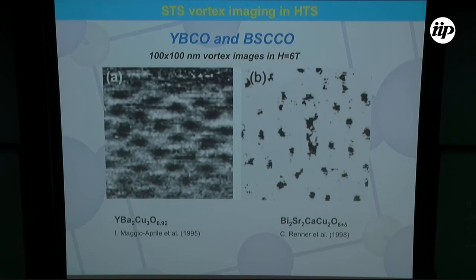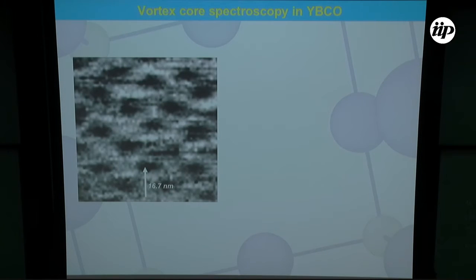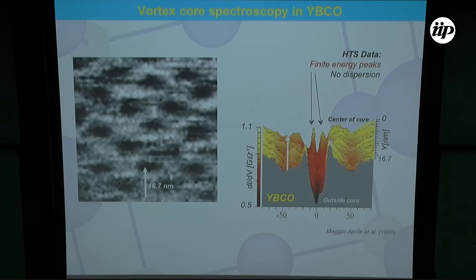Vortices have been seen in a number of cases. This is YBCO and BSCCO. You see the vortices are quite tiny, and you can compare the size of the cores with the ones of niobium diselenide, and due to the fact that the coherence length is really small in the cuprates, the cores appear really small in the images. We usually have non-ordered vortices, so disordered lattices. And for the spectroscopy, this is for YBCO, a trace taken from the outside to the inside of the core will show you this kind of evolution.